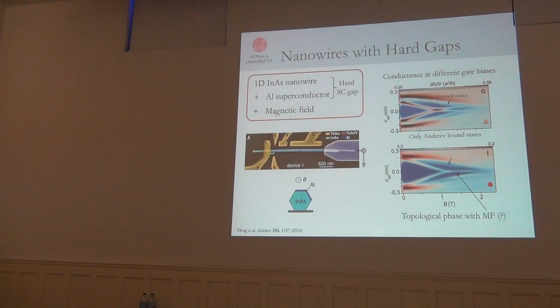I don't want to go into this in detail, but here is a doping regime where you get a state at 0 energy, and we're going to turn up the magnetic field, but then they split up. The interpretation is that these are Andreev states that just cross each other, they are not topologically protected, whereas in the topological phase, they really should stick to 0 here, and this could be the Majorana mode, Majorana fermion, which we are seeing here, because it really sticks to 0.